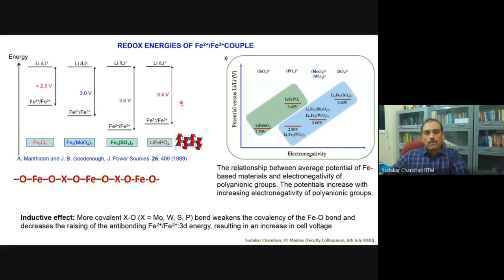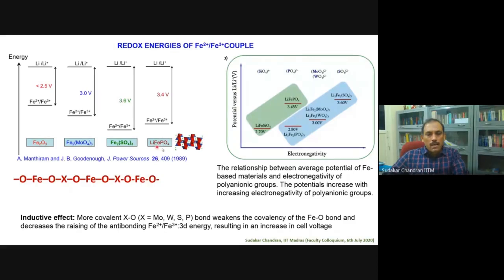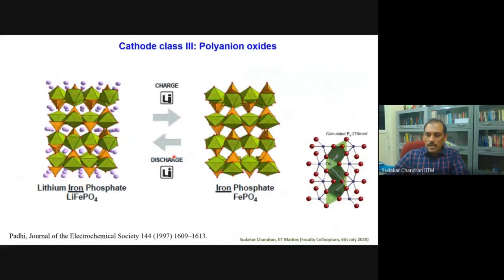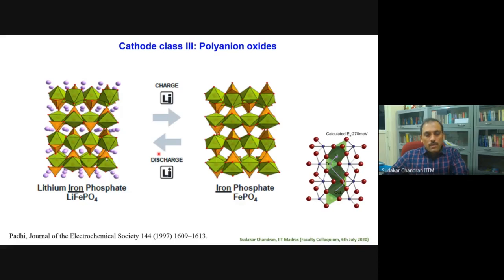With a large number of experiments, though it could exhibit 3.6 volt, it could not be used because the capacity is very low, as it has more sulfate, which is inactive and doesn't help. So they came up with this LiFePO4 compound, and that was another wonderful material. Padhi is the one who did this in Goodenough's research lab. In this particular compound, the lithium moves in and out in a one-dimensional fashion.